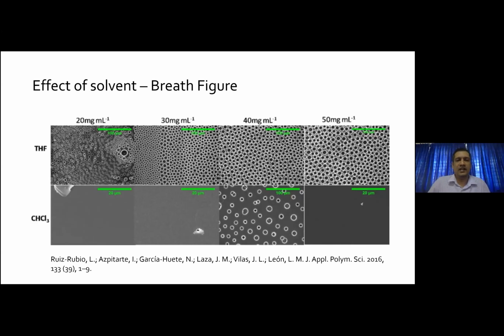What the authors have done is take the same polystyrene, dissolve it in THF and form a thin coat, and dissolve it in chloroform and form a thin coat. When the flow rate is around 20 milligram per liter, 30 milligram per liter, and so on, and you vary the flow rate at a relative humidity of 70%, only the THF showed some kind of droplet condensation and breath figure formation, whereas in chloroform no such pattern was observed, except at the 40 milligram per liter flow rate.